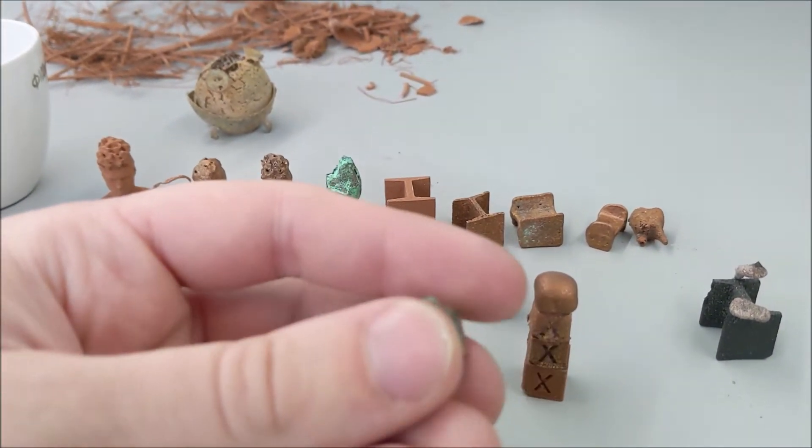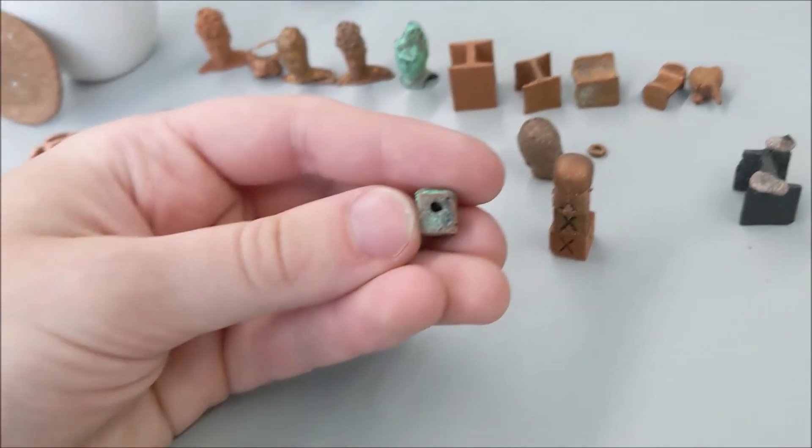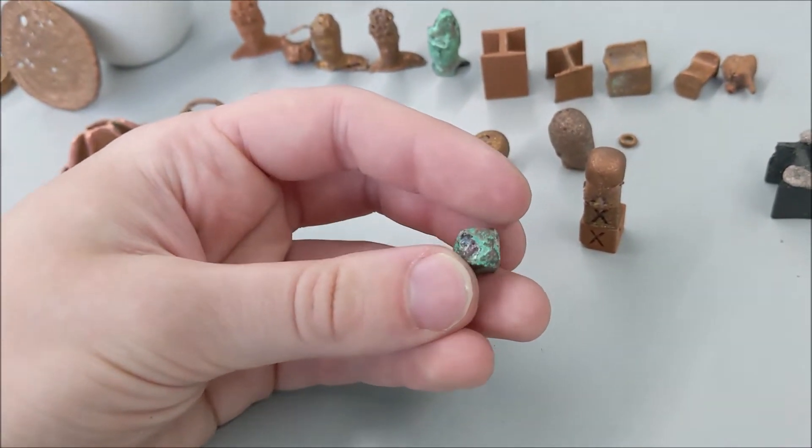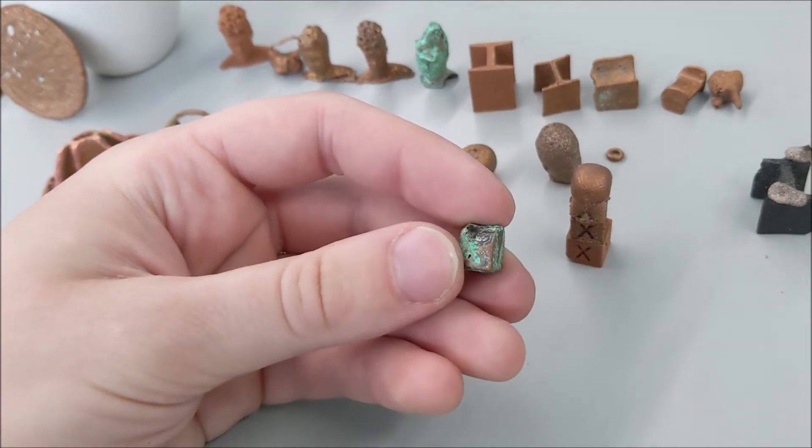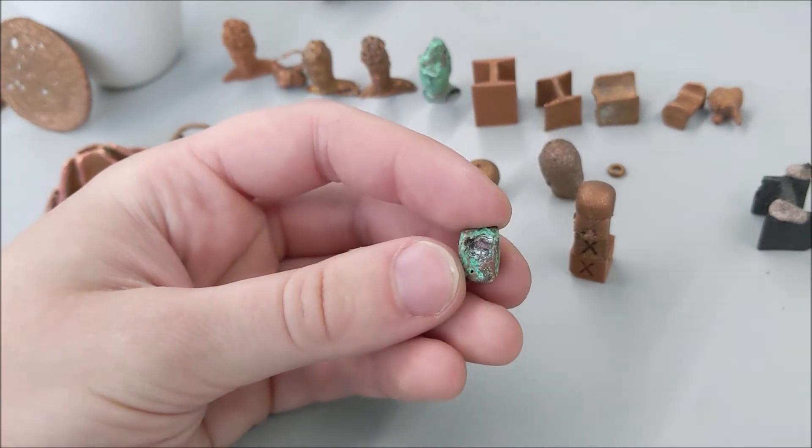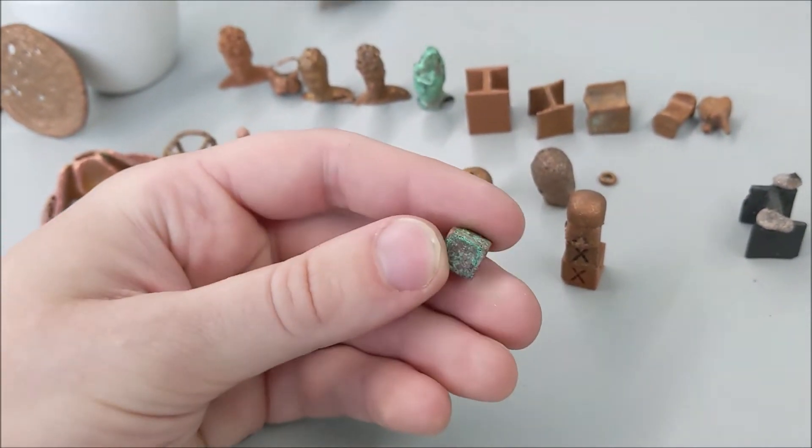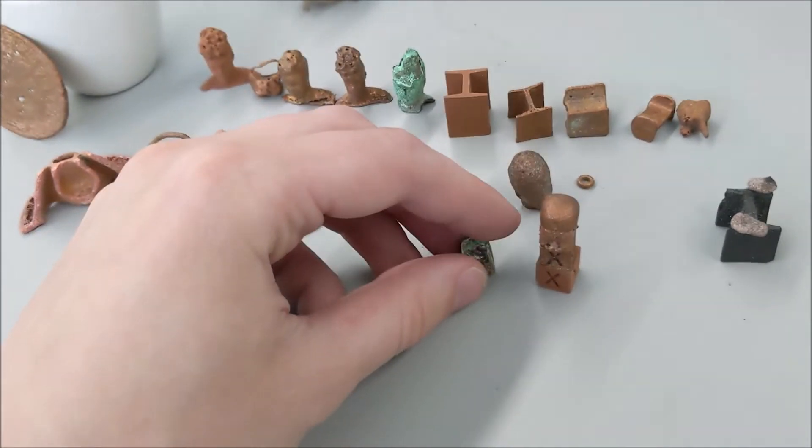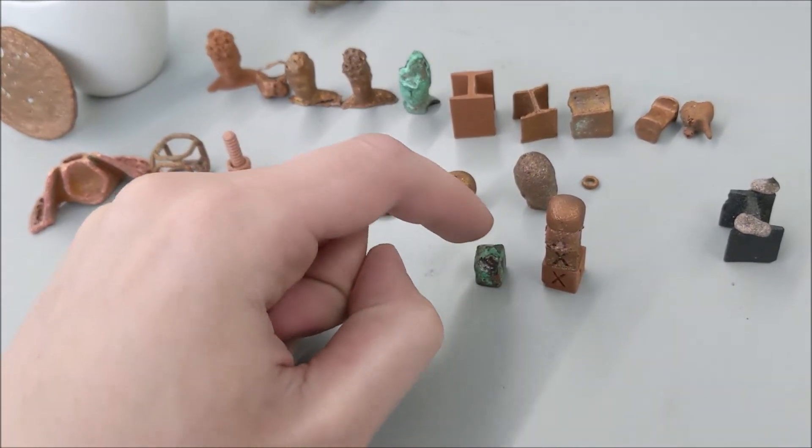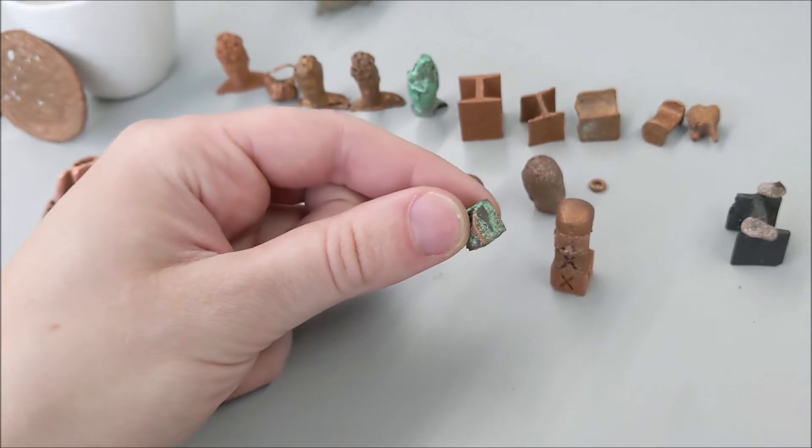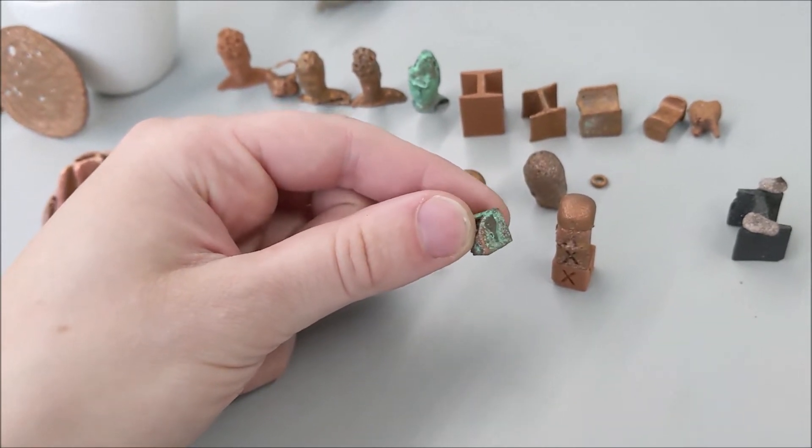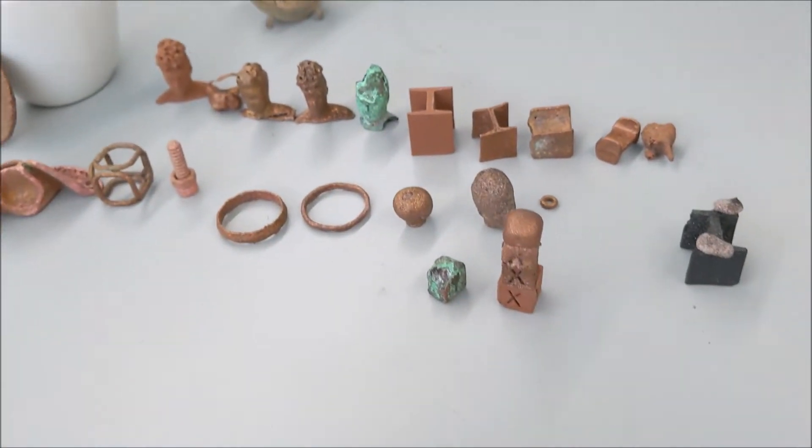Here's another example of an improperly sintered part. This is what happens if you don't have enough carbon in the crucible. And the carbon scavenges oxygen and prevents the part from basically being cooked, because we're not using any special atmosphere. And so the part was eaten away, and then anything that's left over time became very oxidized, carbonated, like with the patina.